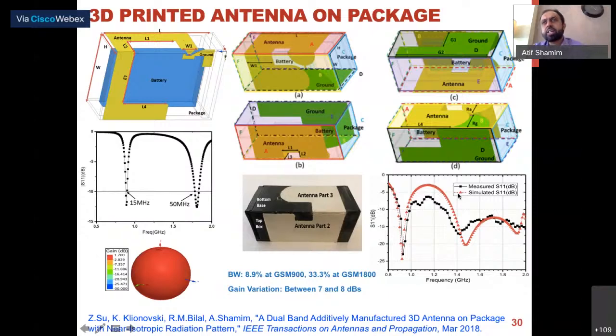Antenna on package, actually it's a combination of antenna on chip and antenna on package example, which I want to show you, is basically when you realize antennas on a chip. You're all familiar with ICs, integrated circuits, and CMOS, they are not a conventional substrates for antenna implementation. This is just showing you the stack up where you have just the space from M6 to M1 to realize in few microns, 8 microns or 10 microns, you need to realize. And the worst thing is that the substrate is very conductive. So most of your power in a CMOS process, if you try to put an antenna there, most of your power gets absorbed by the substrate.